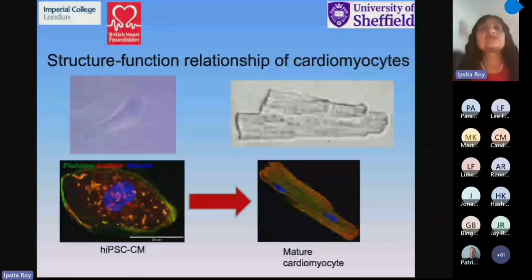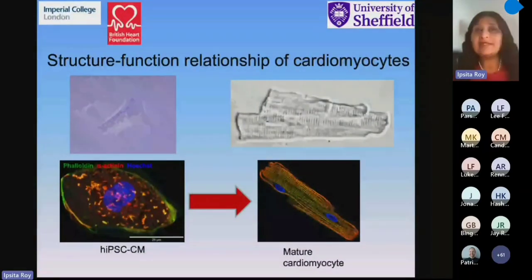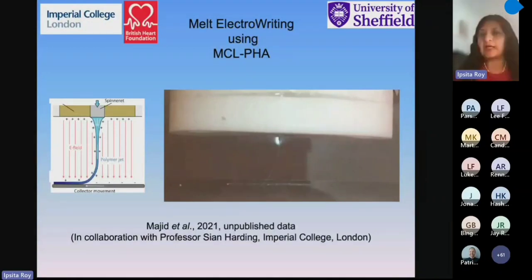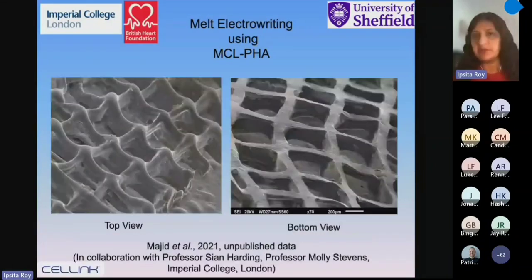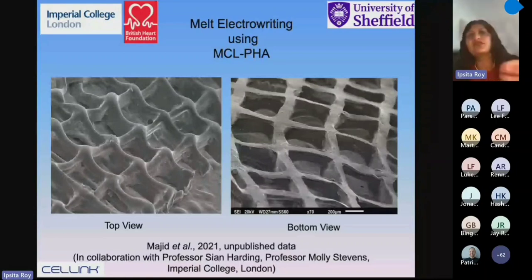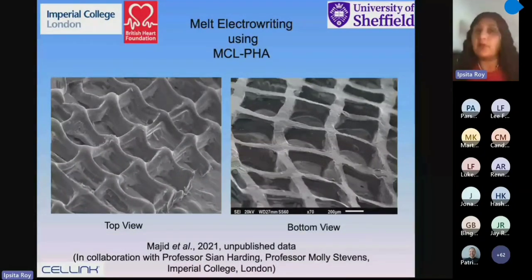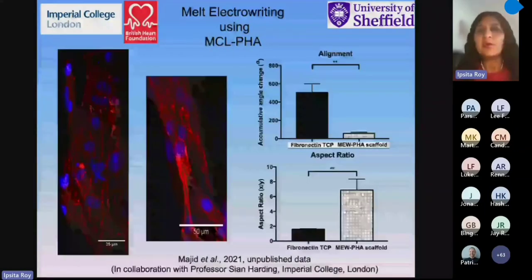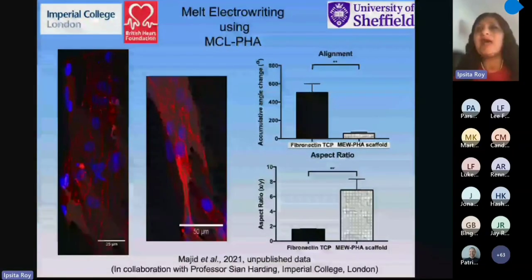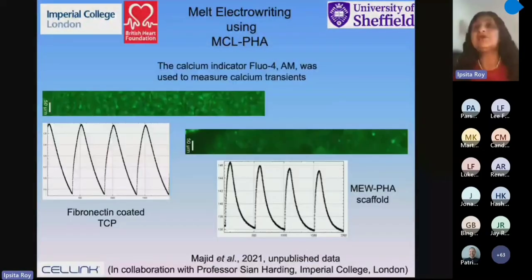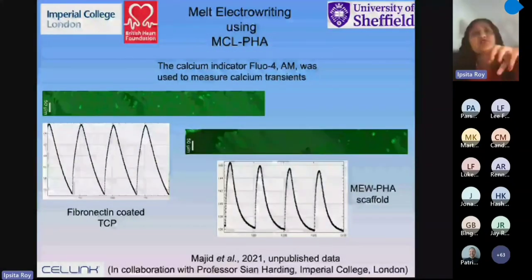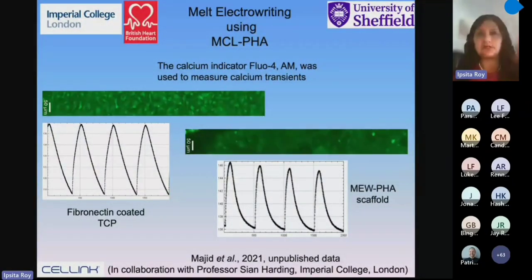So we used stem cells, which you see on the right, and we were trying to get them to become anisotropic, long, healthy adult cardiomyocytes. So we did something quite new in the area, which is melt electrowriting, and these are the sorts of structures we developed. This is an SEM, and as you can see, there are long, thin struts. This is with the medium chain length PHA, which is elastomeric and needed for the heart. And this is what we got: beautifully long, thin cardiomyocytes, which told us that we can use these melt electrowriting patches to mature the stem cells and replace the scar tissue with cardiac cells.